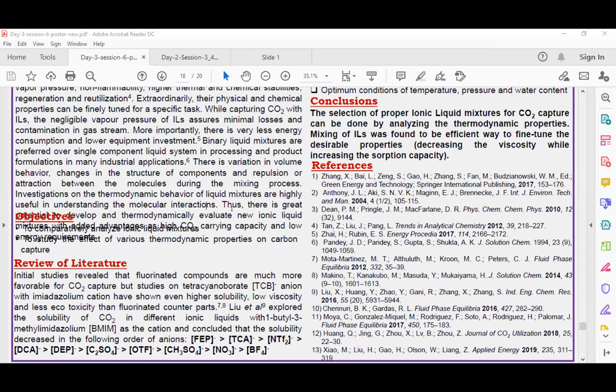Sir. So concludingly, I can say that the selection of a proper ionic liquid for carbon capture can be done by analyzing its thermodynamic properties. For better CO2 solubility, we can have an increase in the alkyl chain length. So the cation having the alkyl chain should have a greater number of carbons. The anion should have higher molar volumes, and the binding energy for the cation and anion should be low. Viscosity values should be low. For the mixtures, we should have a positive deviation from ideality. So mixtures with positive excess volume can be used for carbon capture for the better. And moreover, temperature, pressure, and water content can be used at the optimum conditions to get the maximum value of the CO2 solubility. That's all from my side.